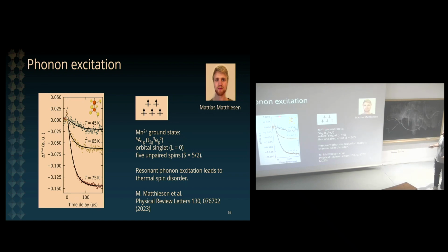So in this material, manganese 2 plus in its ground state is in an orbital singlet state, which is L equals 0. And this is due to the fact that we have 5 unpaired spins. So we have a total spin of 5/2, but the orbital part of the system is in a singlet, L equals 0. Okay. So the system has strictly zero spin-orbit coupling at equilibrium because there is no orbital momentum. Okay. So in this material, a resonant phonon excitation is only leading to thermal spin disorder.